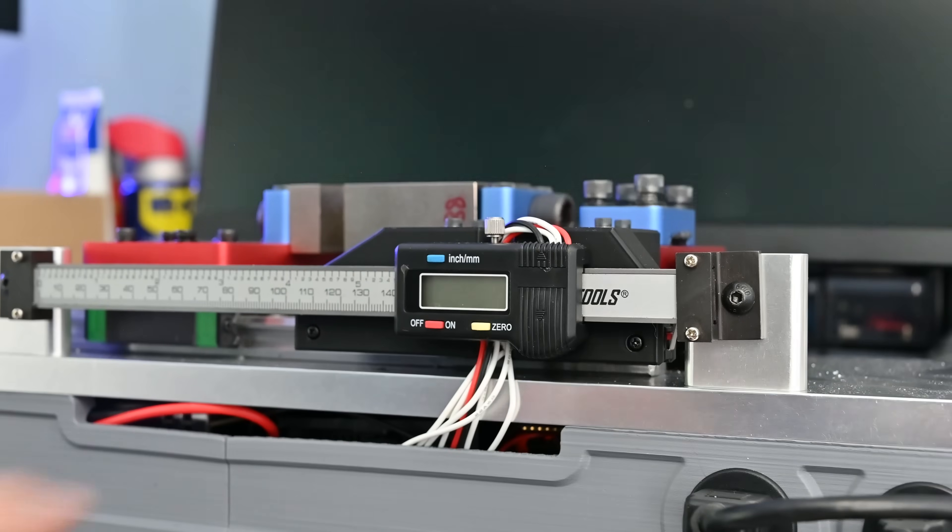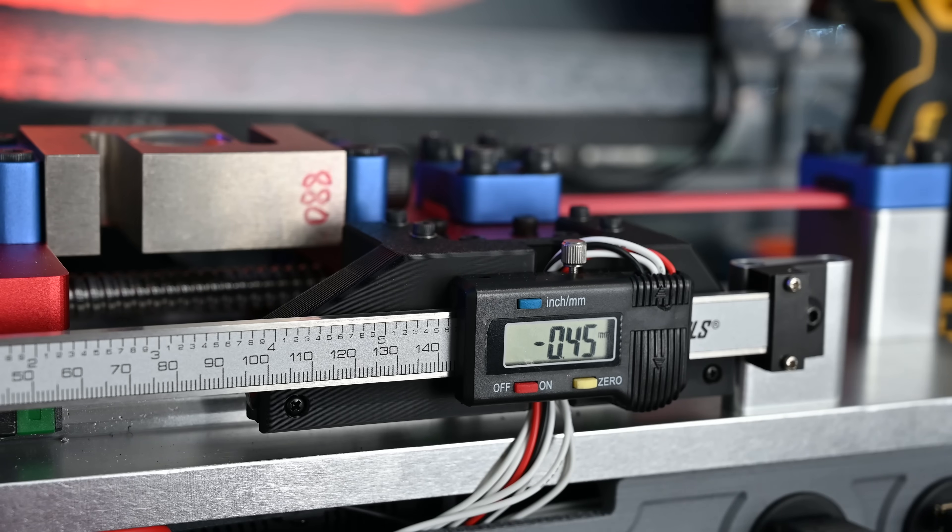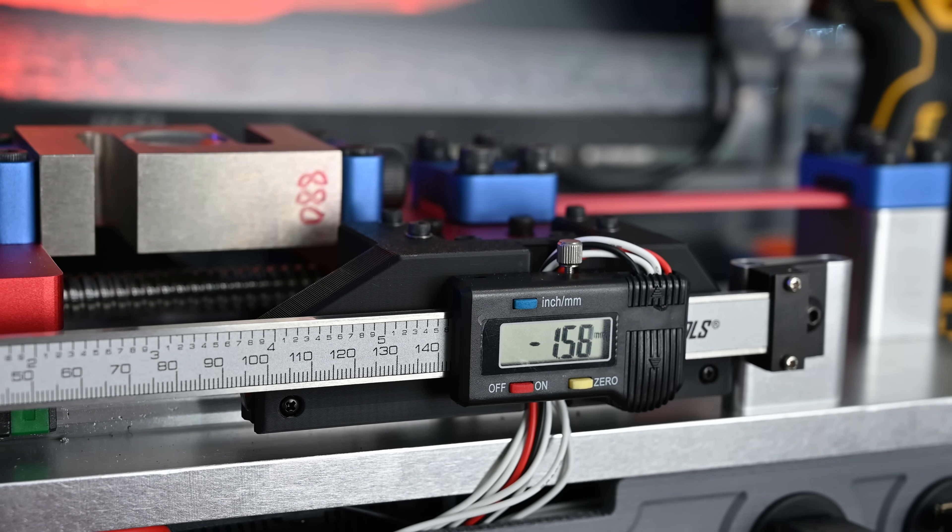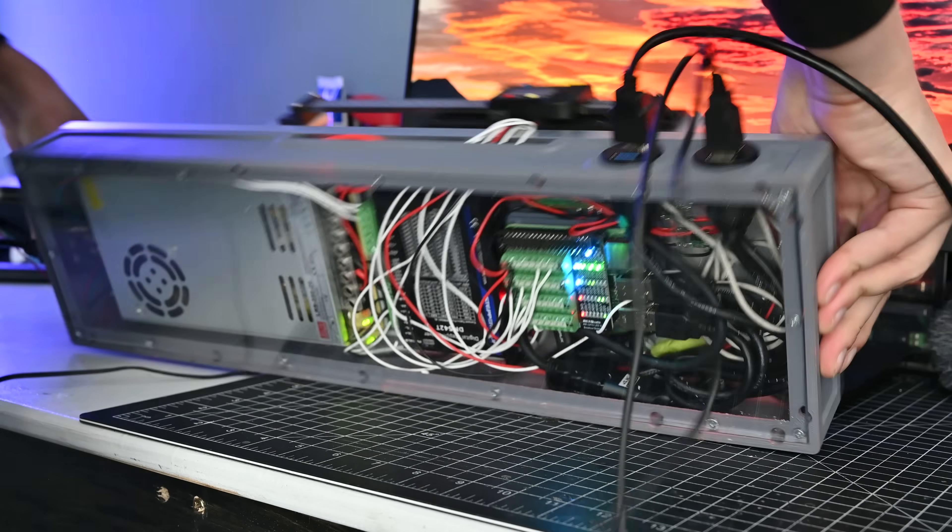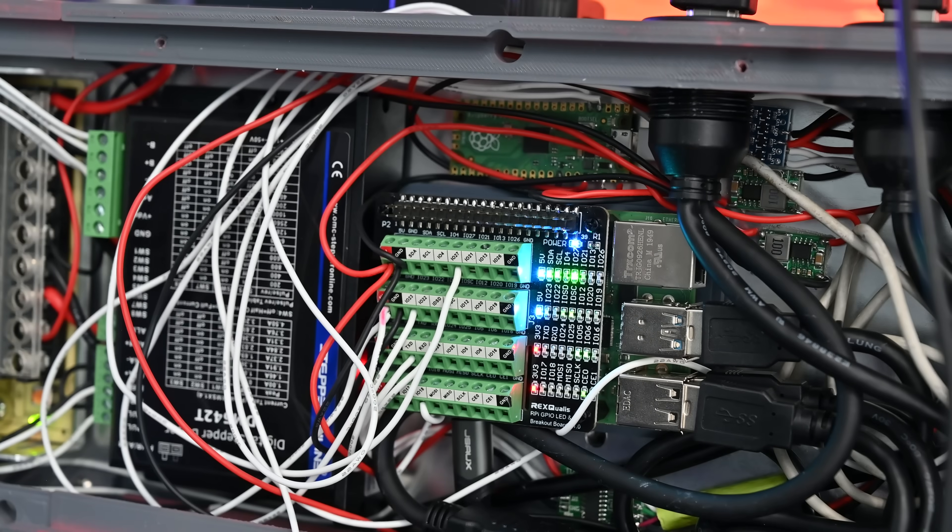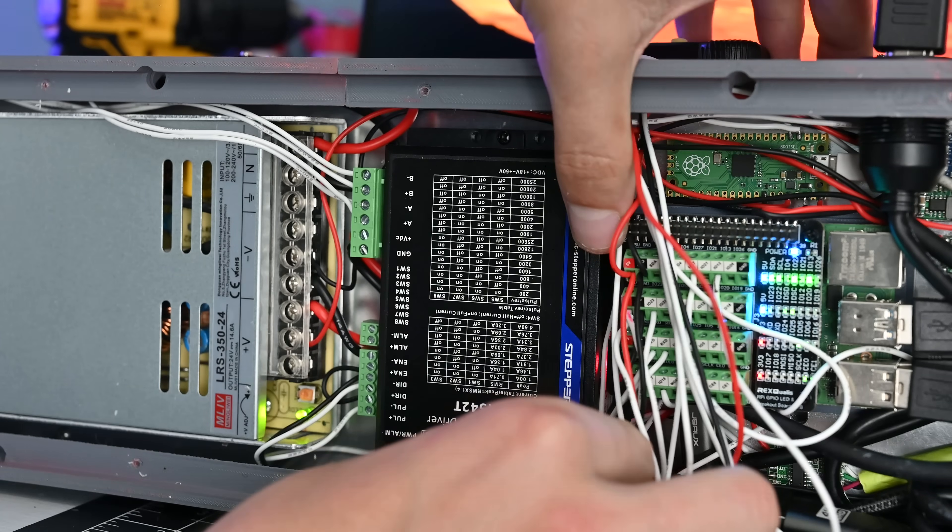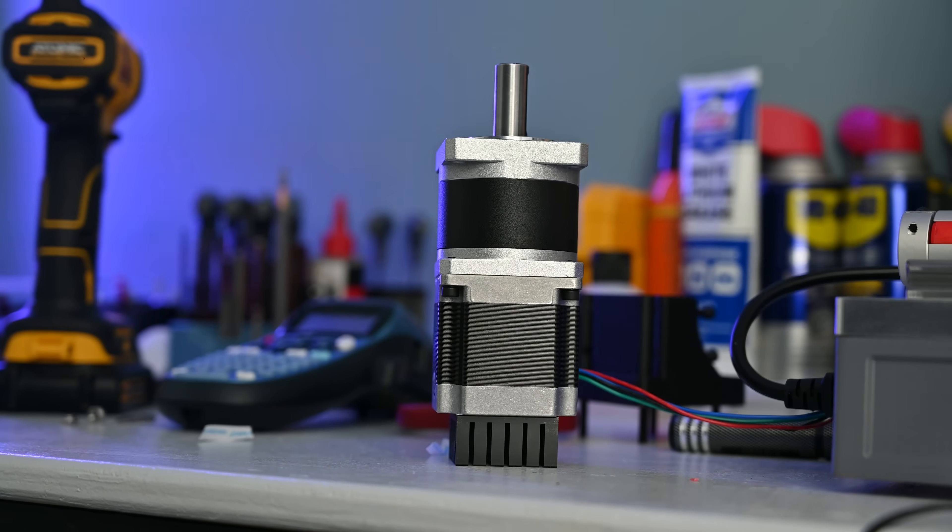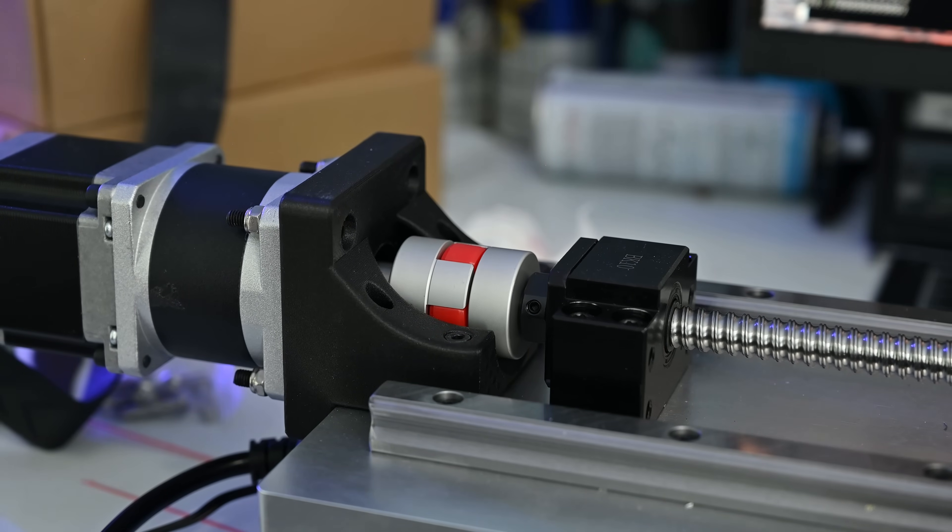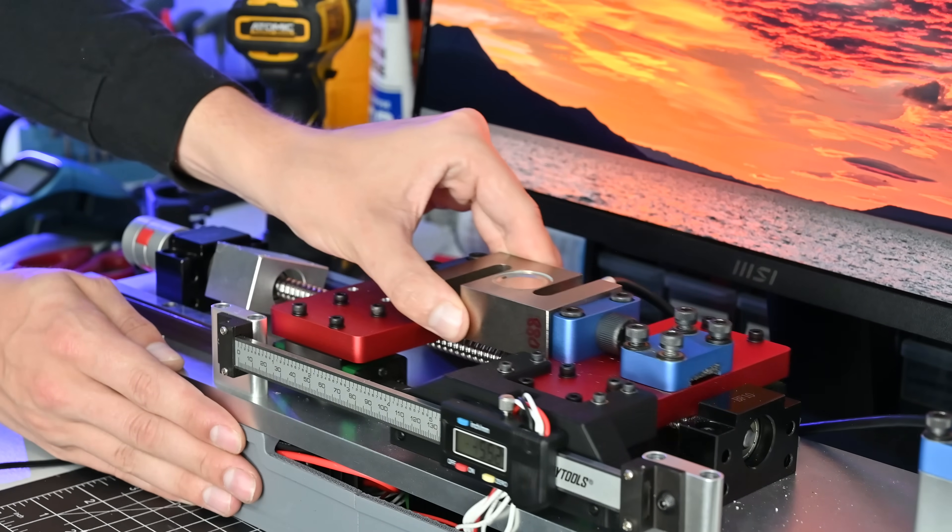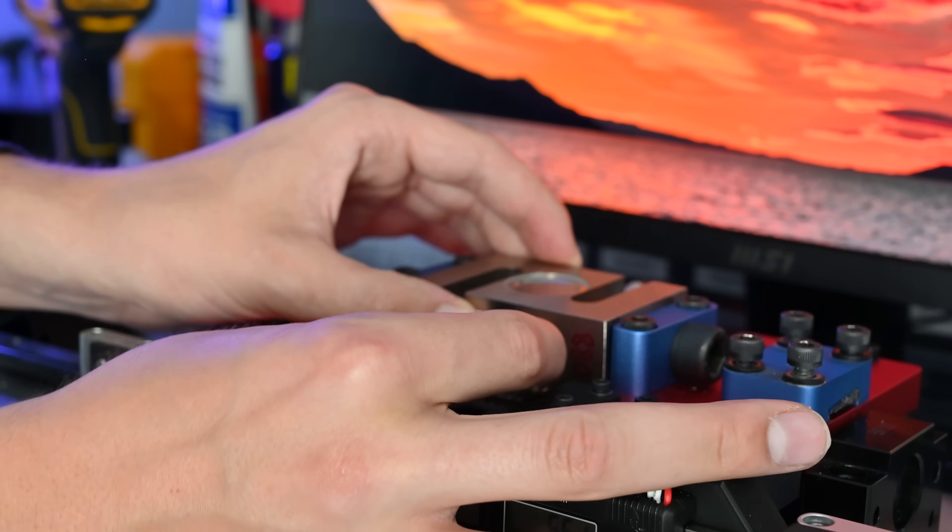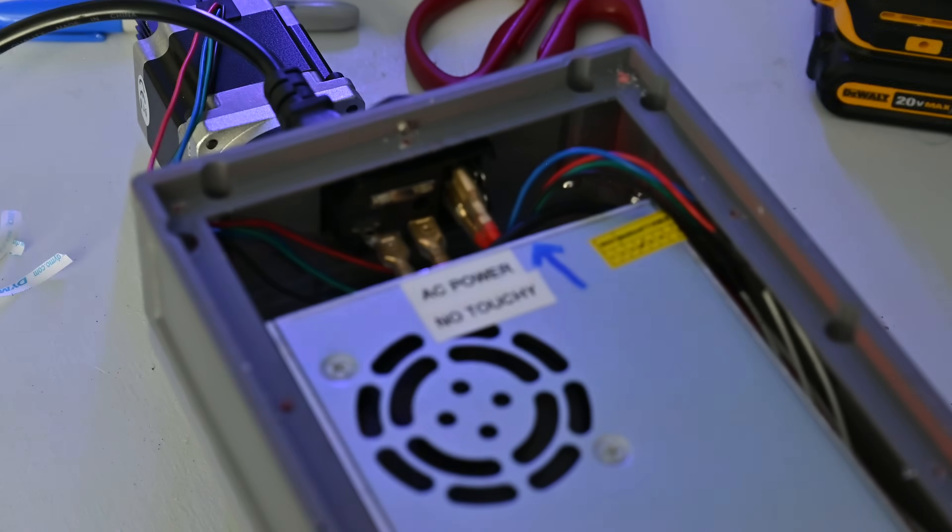This project required a ton of hardware, electronics, and software integration but in the end the system works pretty well. Now I know it's boring but very quickly I want to explain how this works because it's kind of cool. A Raspberry Pi controls the whole show and sends step commands to a stepper driver which then sends the correct signals to a geared NEMA 23 stepper motor. The motor turns a ball screw which pulls on these two carriages attached with a load cell. This is a 500 kilogram load cell and the Pi reads it at a fixed logging interval to give us good consistent data.